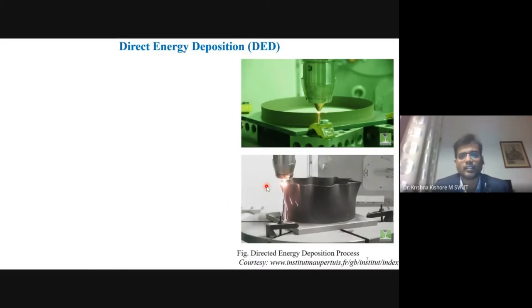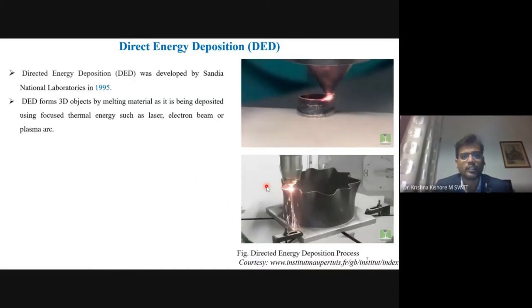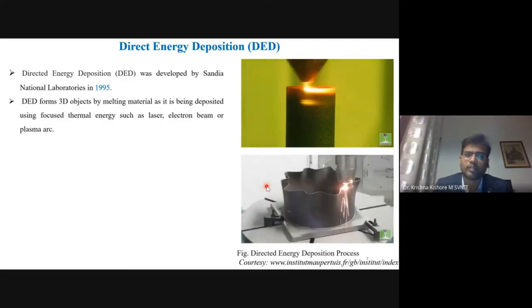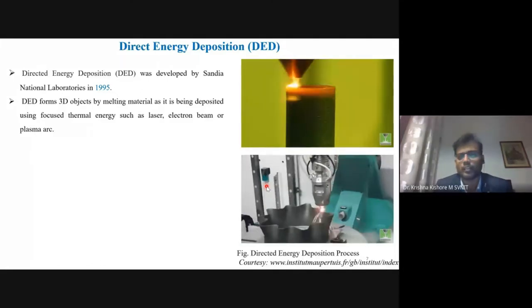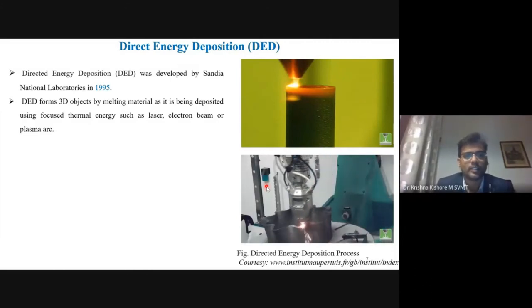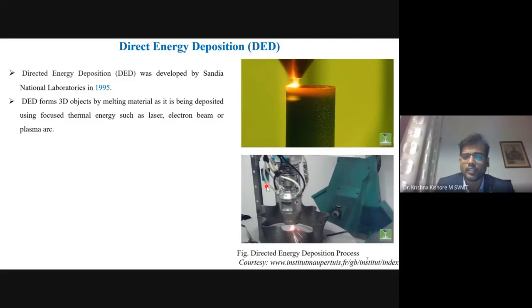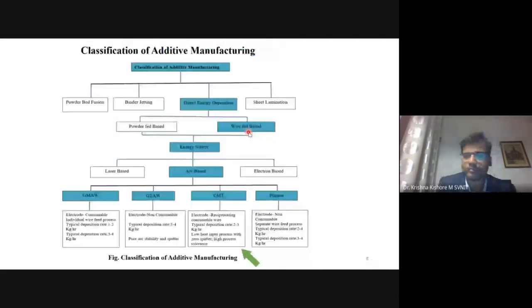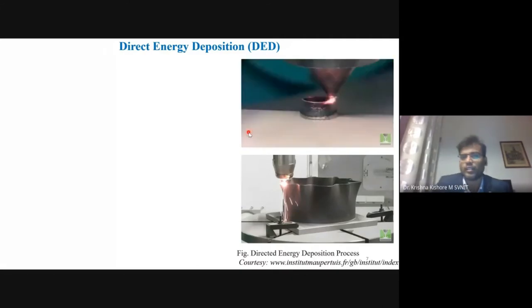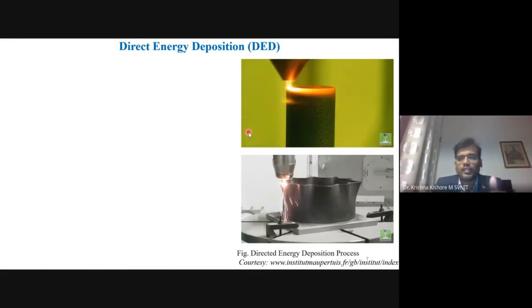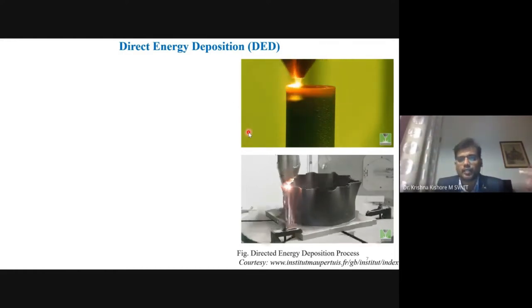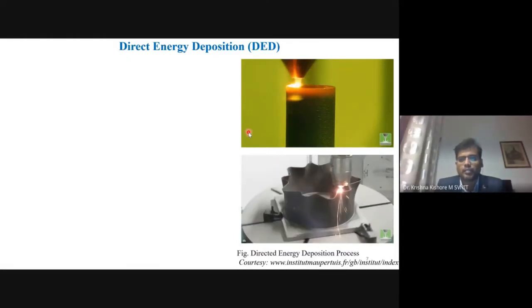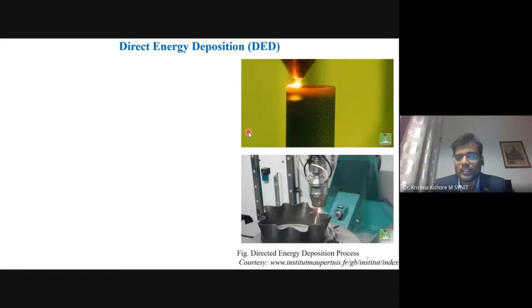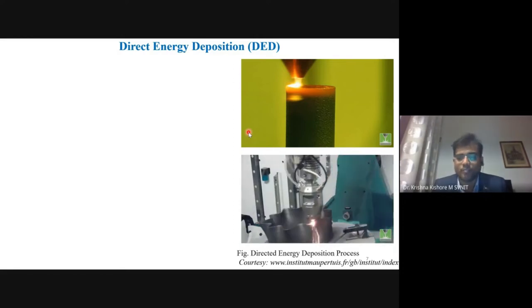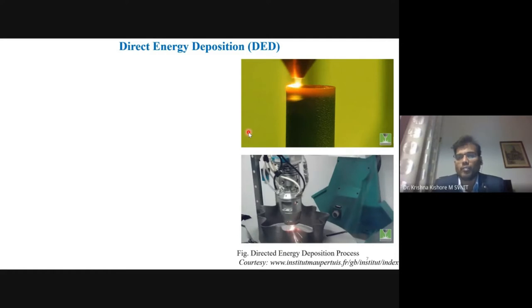Now, as I said, it comes under the category of direct energy deposition. Direct energy deposition is also a little bit of an older process. It was developed at Sandia National Laboratories in 1995. If you see on the right hand side, there is a laser coming out, and the powder is fed coaxially towards the laser beam. When these particles hit the laser beam, they melt and get deposited. You can see how quick this process is and at how much faster a rate we can deposit the molten droplets.